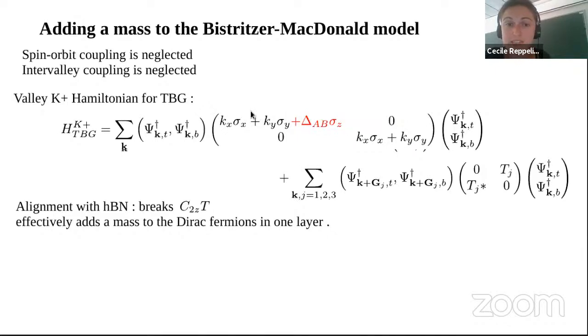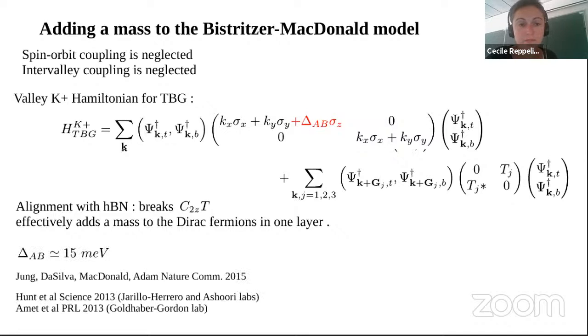Note that I've only added it to one layer and not to the other, because typically only one of the graphene layers is aligned with the substrate for practical reasons. But this is enough to open a gap in all of the Dirac cones. The amplitude of this gap, this mass, is around 15 milli-electron volts. This is a gap that was experimentally observed in these experiments and later analyzed theoretically.